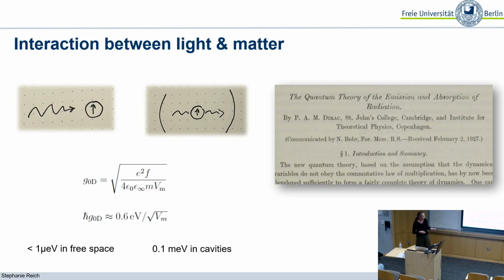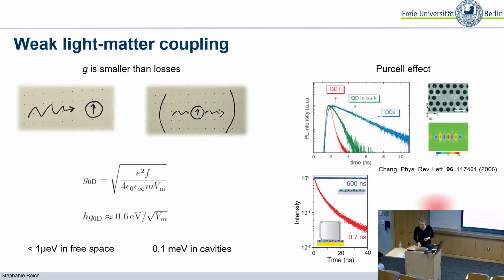And if you consider a mode volume for a photonic cavity, so something that's bound to be lambda to the power of 3, then you will find that you can increase from 10 to the minus 6, you can go to 10 to the minus 4 light-matter interaction in this type of photonic cavities. So this is still pretty weak interaction, but even for this still weak light-matter coupling, you can already see an effect of the light field on the properties of materials. And one of the most well-known ones is the Purcell effect, and it tells you that the spontaneous decay of an excited emitter will depend on the light-matter interaction strength.